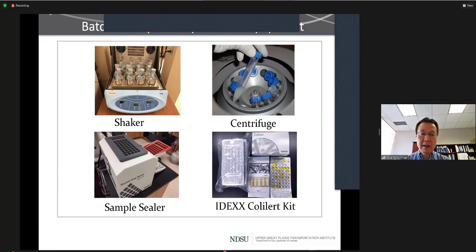We use a temperature controlled shaker to conduct the batch experiment. And we use a centrifuge to isolate the E. coli culture such that we can prepare the diluted solution for our experiment. And we use IDEXX and the sample sealer to determine the E. coli concentration before and after the treatment.